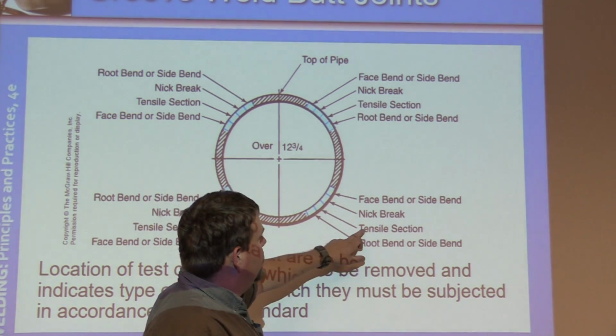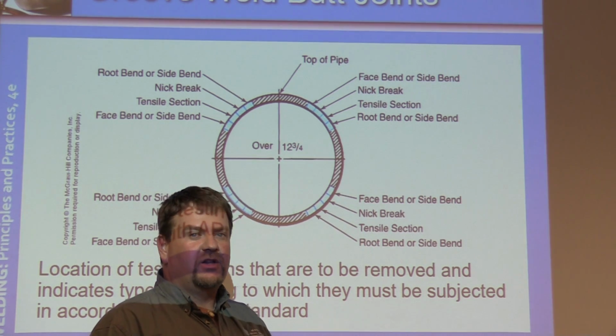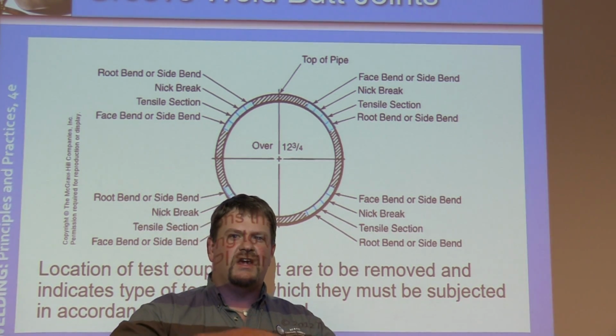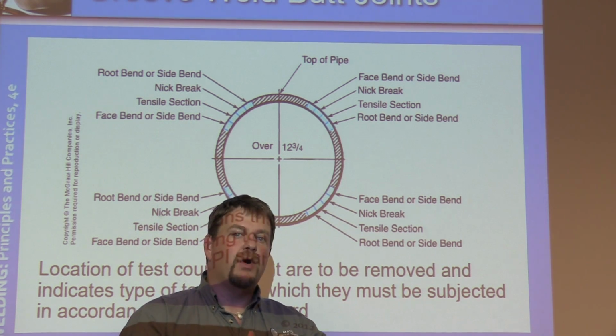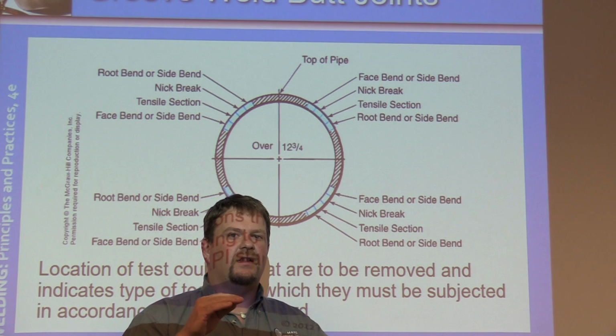Then we're also going to take a tensile section. So we're going to put it in a tensile machine and measure how much force it takes to pull apart. Now it also has to break outside of the weld zone, and if it does break within the weld, the pressure it breaks at has to be at least above the tensile strength of the pipe.